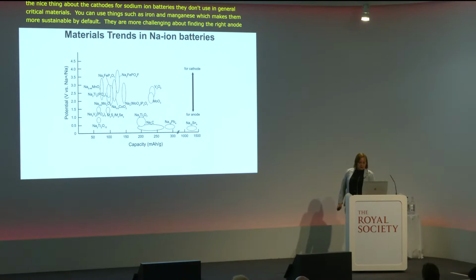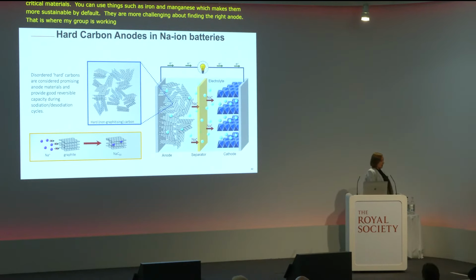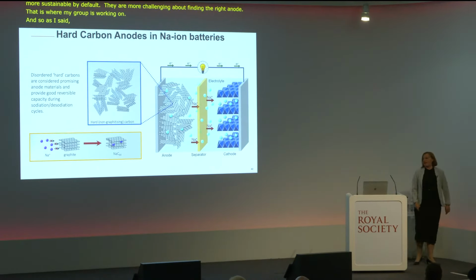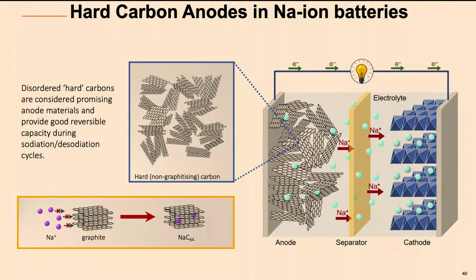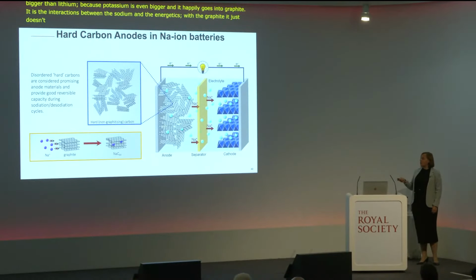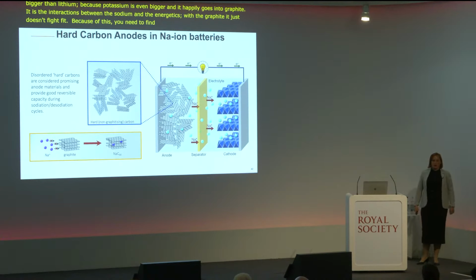As I said, in a lithium-ion battery, you use graphite as the anode. But unfortunately, graphite cannot store sodium. And the reason is not necessarily that sodium is bigger than lithium, because potassium is even bigger and it happily goes into graphite. It's the interactions between the sodium and the energetics. With the graphite, it just doesn't quite fit. And so because of this, you need to find different materials to use as an anode.